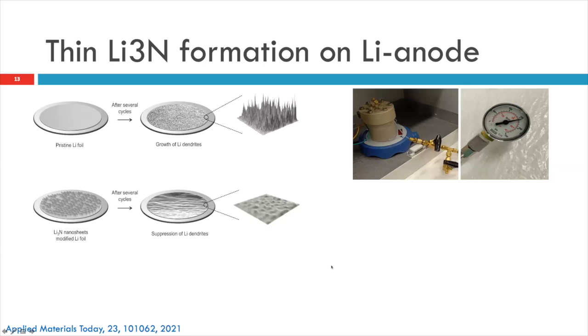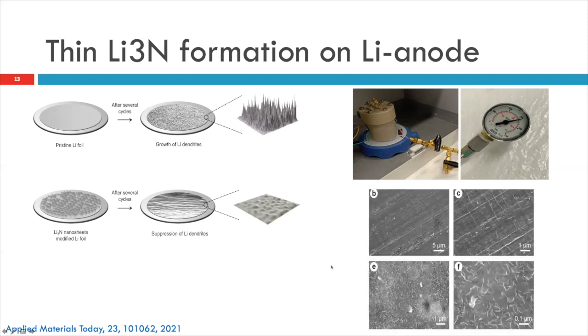Here we have done something different, in a very simple way. We saturated nitrogen gas in a liquid electrolyte and then dipped our lithium metal, and in a very controlled way formed this lithium nitride deposition on the lithium metal, as a very thin film. We have done AFM and looked at the roughness of the lithium nitride, and it has shown that a very thin and not very rough surface was created. The AFM images also show that very uniform lithium nitride deposition happens, and lithium nitride is well known as a lithium conductor, and we feel that it may be preventing the lithium dendrites.